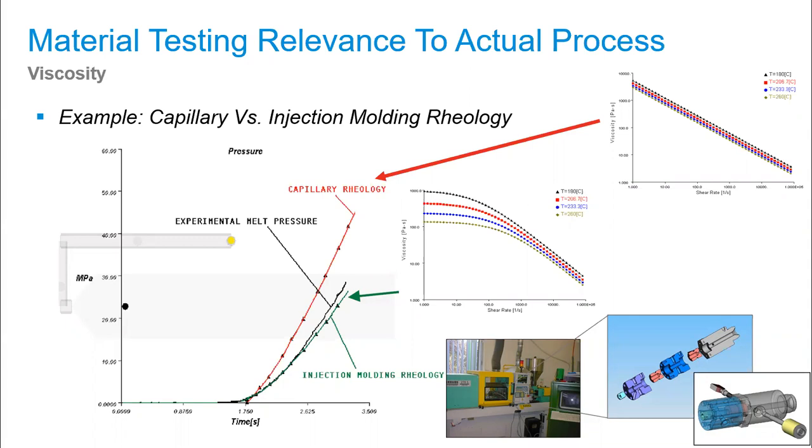And we also get the history. Now, we talked about fiber breakage in the barrel, but the heat history of the material is very similar in an injection molding rheometer, versus a capillary rheometer, where you just kind of put pellets in, let them melt for a dwell time, if you will, and then apply pressure. So we essentially just try to make sure that they're melted. And again, we said that dwell time affects properties. So we're inherently having some residence time built in just to melt those pellets, and we don't have the same heat history as we would in injection molding. So we typically find that the injection molding rheometer gives us a more accurate injection molding simulation because it's using the same process.